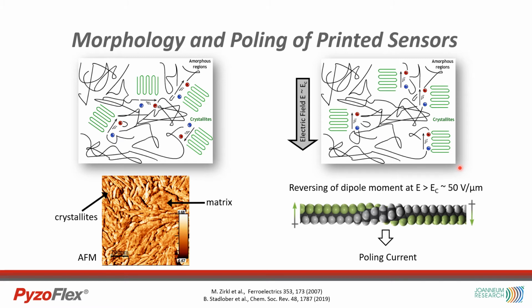Under opposing electric fields larger than the coercive field, which is about 50 volt per micrometer in PVDF, the dipoles reverse their orientation repeatedly, which is illustrated here as an axial rotation of the polymer chain.